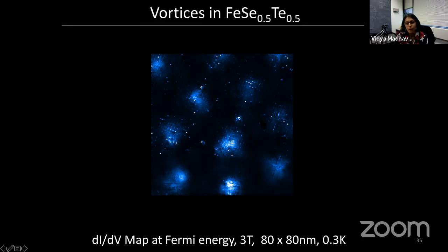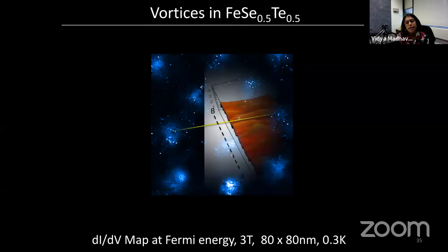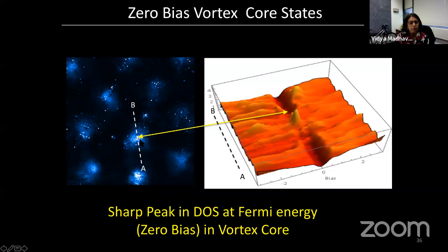These vortices want to move a little bit, just a tiny bit. And so all the dots and the streaks that you're seeing in this vortex map are the fact that the vortices want to move a little bit. In any case, if you go to one of these vortices and take a line cut, far away you see a nice superconducting gap, and as you go through the center of the vortex, you see a very sharp peak in the density of states, which is centered at 0 bias.